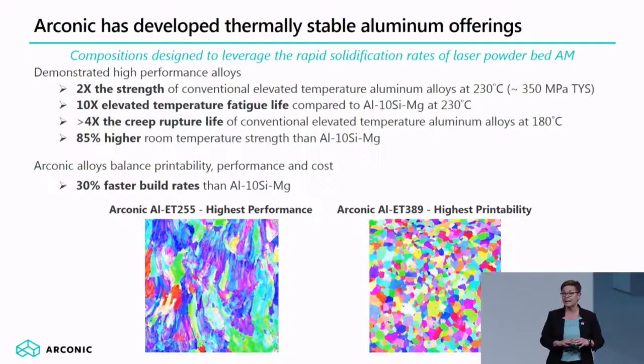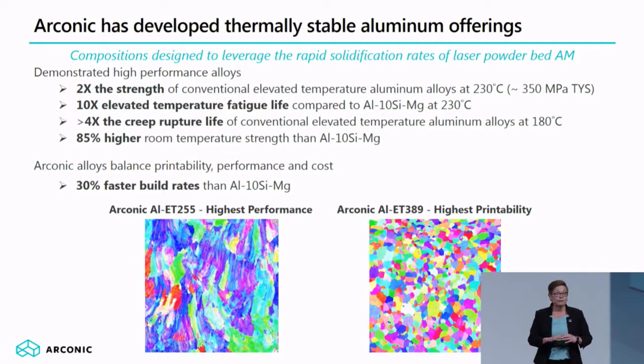And of course, at elevated temperatures, creep resistance is also important. Creep, of course, is the material's deformation and eventual rupture when subjected to high stresses at elevated temperatures. Our highest performing alloy actually exhibits more than 4 times greater creep rupture lives than the conventional 2000 series alloys. The alloy is also suitable for room temperature applications for structural components due to its 85% higher strength at room temperature compared to aluminum 10 silicon mag.